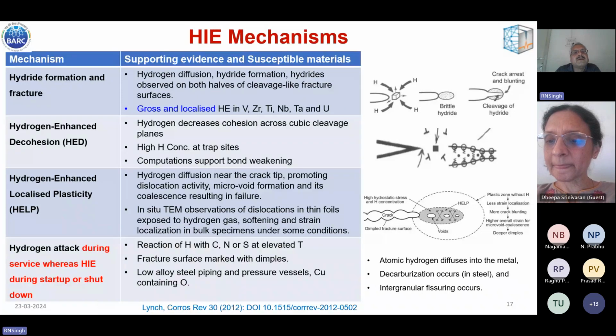Yeah, you rightly said, in case of hydride forming metals, conducting the experiment is much easier. In fact, for zirconium alloys, we determine this DHC velocity regularly. There, hydrogen does not come out of the metal system so easily. If you recollect, there is something called the pressure composition isotherm. On the y-axis you have partial pressure of hydrogen, on the x-axis concentration of hydrogen, and initially it increases linearly, then shows a plateau, and then again increases linearly. This plateau pressure decides that if partial pressure outside the sample is more, hydrogen will go from the environment to the metal, and if partial pressure is less than the plateau pressure, hydrogen will come out of the system.